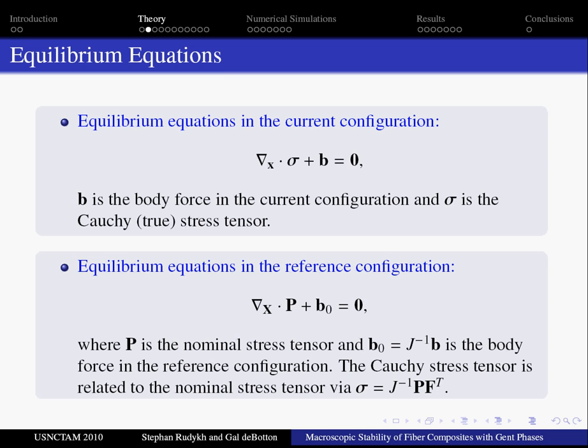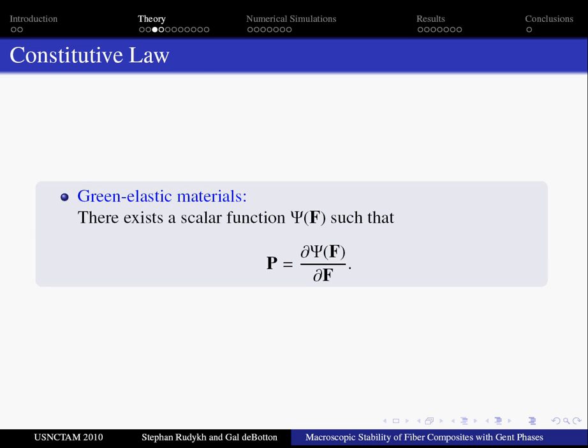In our work we consider the so-called green elastic or hyper-elastic materials, that is we assume that there exists a scalar strain energy function, psi, such that its derivatives with respect to deformation gradient produce the nominal stress tensor.